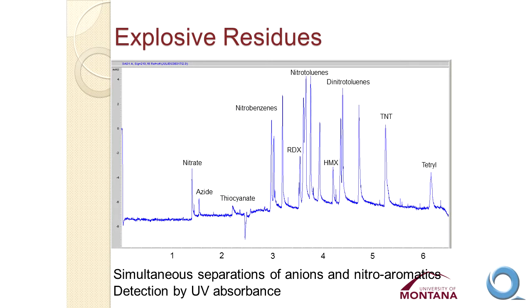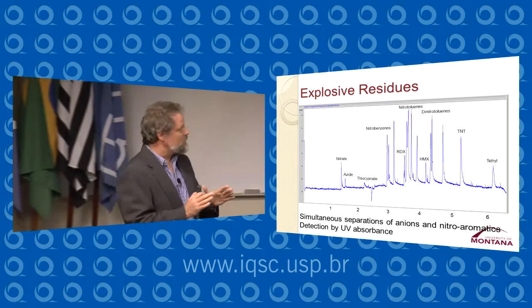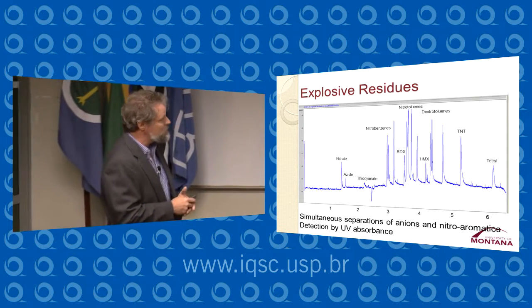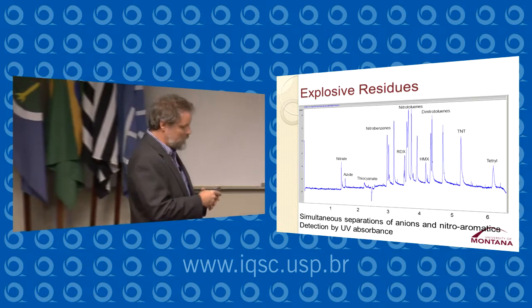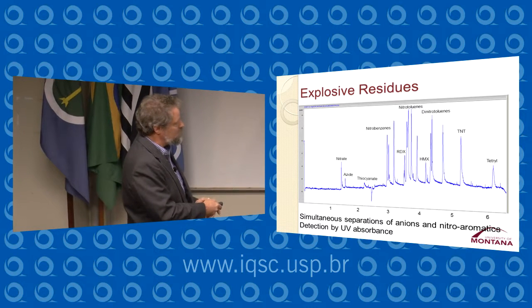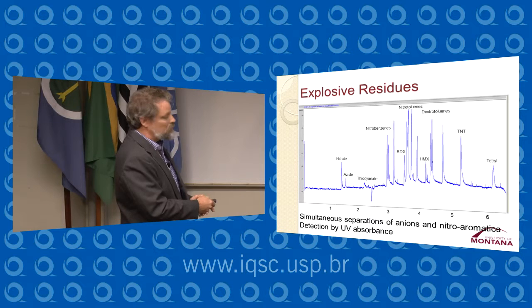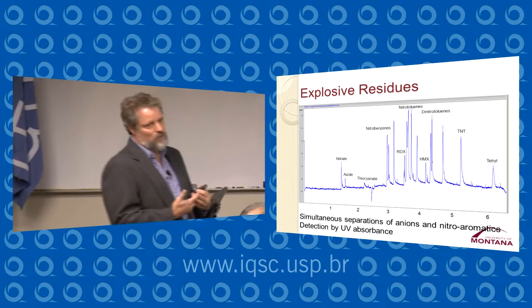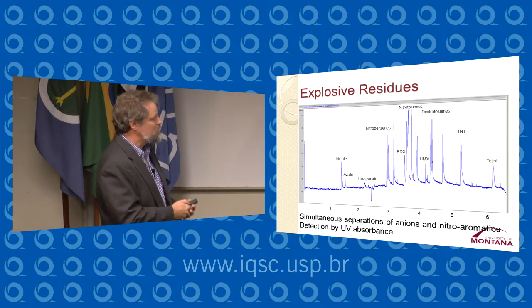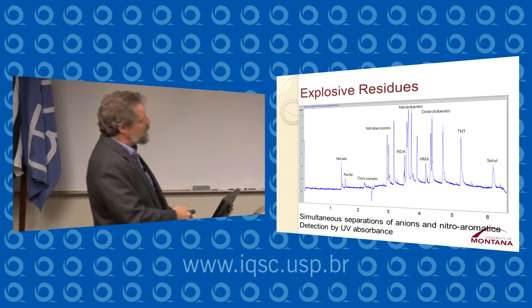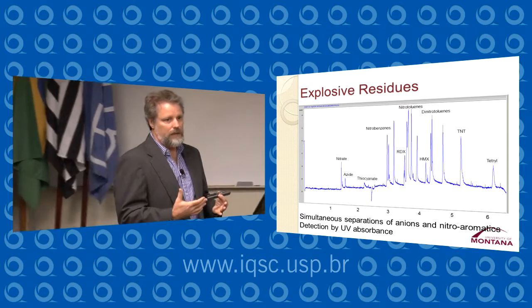The application that she's working on is a simultaneous analysis of anionic and nitroaromatic compounds that are found in explosives and in explosive residues. So the idea here is to use a single capillary or a single channel to achieve the separation of both the anionic compounds and the aromatic compounds. And so this is very early in this process. She just generated these data last week. But basically, here she has the separation of the anionic compounds, and they are separating purely by electrophoresis. They're not interacting with the nanoparticles. And then these compounds here are all being separated by interaction with the cationic nanoparticles that she's developed.